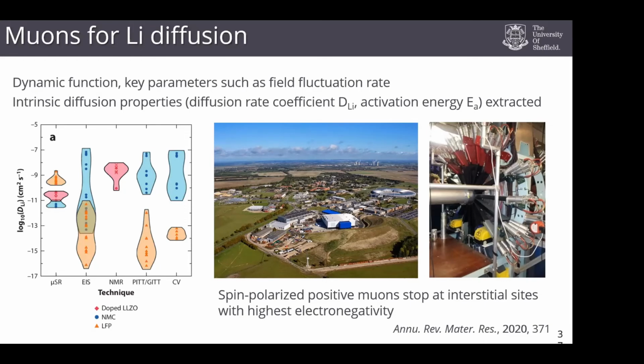There's lots of ways to study lithium mobility. You can use impedance spectroscopy, you can use NMR, you can use galvanostatic type of experiments. But what this graph is hopefully showing is that even in a single type of material, here just lithium iron phosphate, I've got a huge change in the reported values for lithium diffusion in the literature.